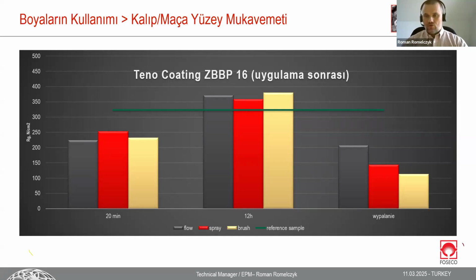And the right side of the graph shows us that if the coating is applied and immediately put on fire, we can say the original strength is cut on average by 2. It's less than half strength. So it means that the surface of the mold or core is super soft. When we talk about quite massive cores or molds, we will not expect big problems. But if we talk about high temperature alloys and a damaged surface, we can expect some scabbing, some penetration, because the strength of the surface is not enough.